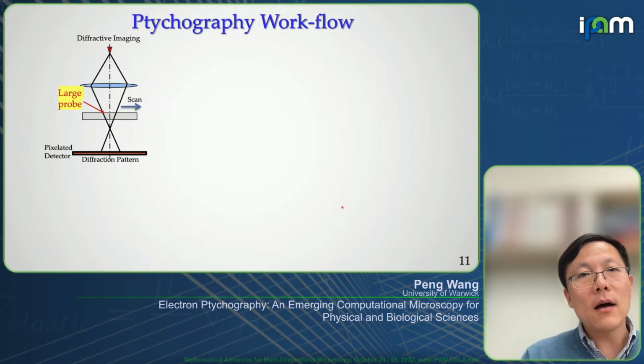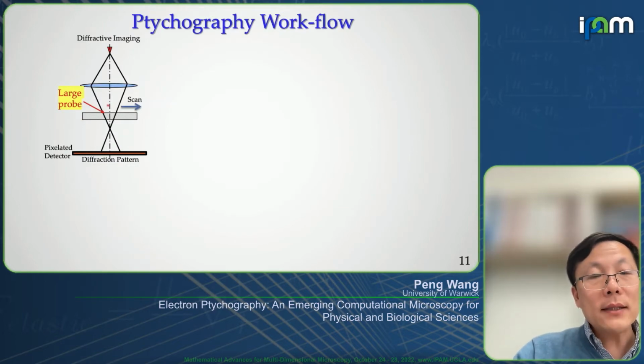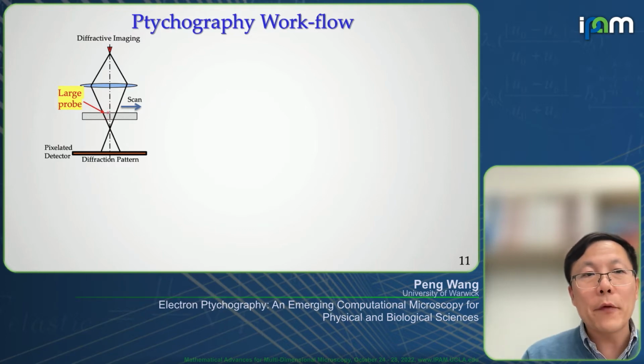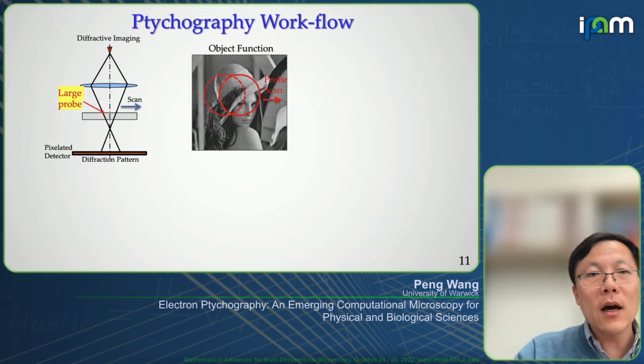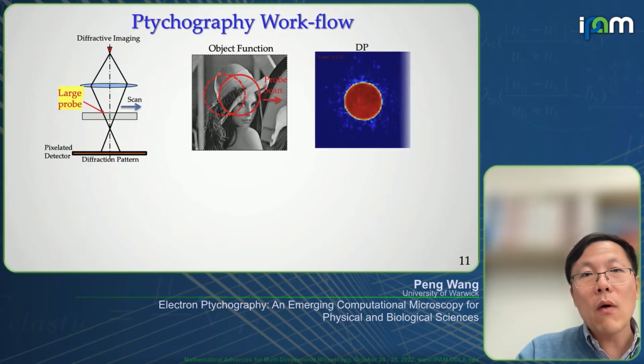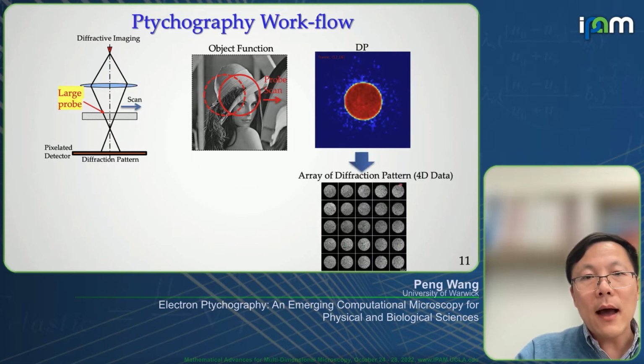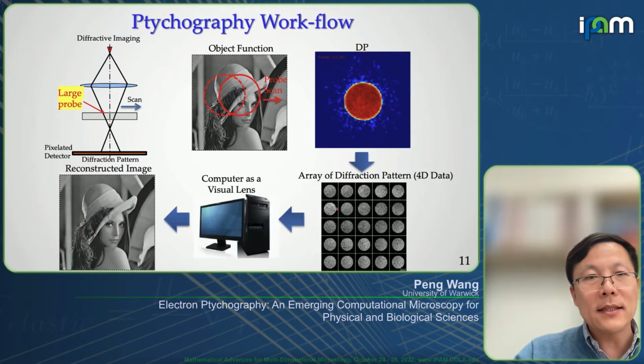This is the workflow, as you can see. Rather than forming an atomic-size probe, here we use a largely defocused probe so that you have a large probe size incident on the sample. Therefore, you can scan along the sample with a relatively large step size. At each probe position, we acquire a two-dimensional diffraction pattern. Because we scan this probe two-dimensionally, we form an array of diffraction patterns.